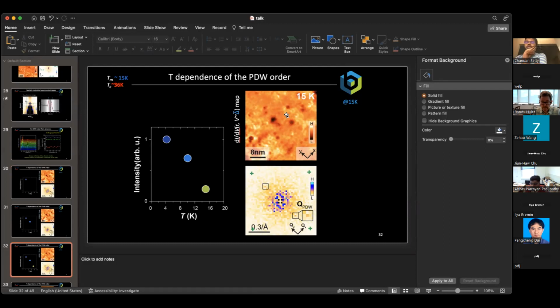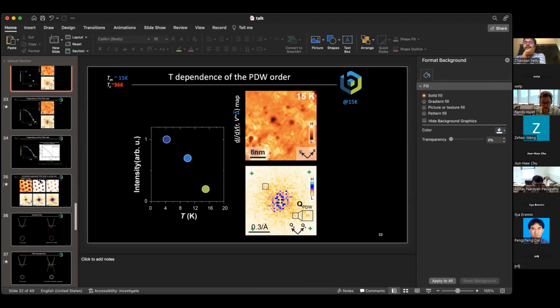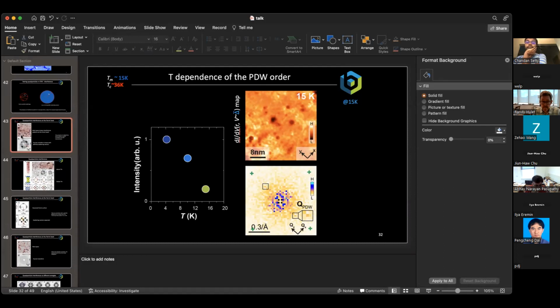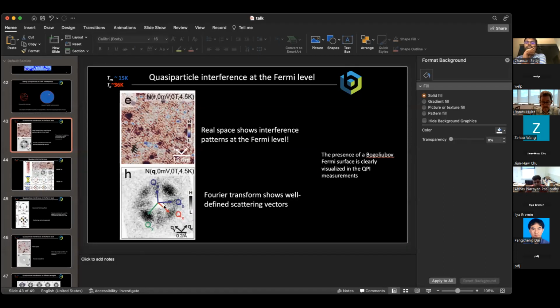Yeah, so I was wondering, you call it a Smectic, and there is a directionality in the Q, but somehow the QPI spectrum seems to have a fourfold symmetry. So I'm wondering how you reconcile the two. Yeah, actually, it does not have a fourfold symmetry. If you look at this carefully, you'll see that this spot is much more intense than this spot. And the angle here is also not exactly 45 degrees with respect to this angle. So it actually breaks the fourfold rotational symmetry. Okay, thank you. Randy?